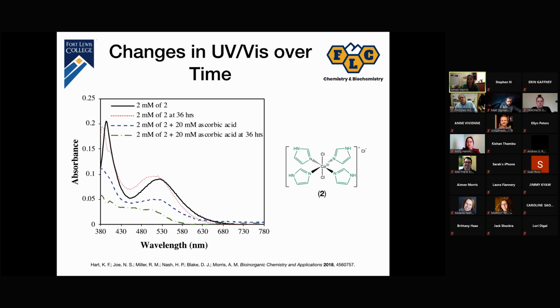The only things that were in that cuvette were water and our compound that we had assigned as that trans chloro with the 4 imidazole ligands. So the most likely thing to be happening is that the ligand exchange is involving removal of a weak field ligand like a chloro ligand and replacing that with a stronger field ligand like either imidazole or aqua. And so we saw this visual color change happening.